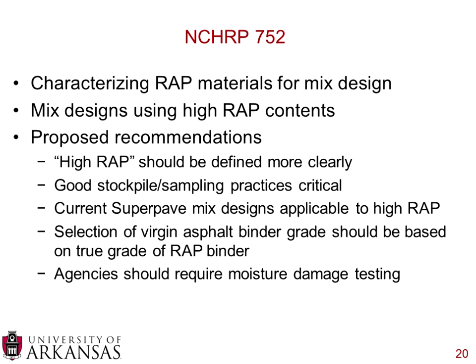I stated it as about 20%. Some other agencies in some other locations do 25 or even up to 30%. So there's really no standard definition for high RAP usage. They emphasize that good stockpile and good sampling practices are absolutely critical. This makes a lot of sense when we're talking about RAP coming from potentially many different sources, having to be processed in the plant. You want to make sure that you're managing those stockpiles and you're managing how you sample them well. They do believe that current Superpave mix design rules and procedures are applicable to high RAP. You can simply use the RAP as another aggregate source.